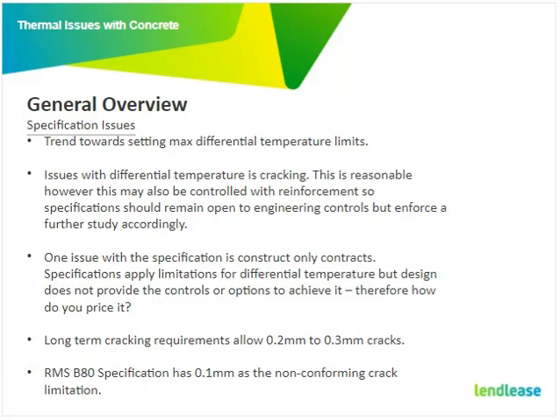Also, for differential temperature, there are long-term cracking requirements that allow up to 0.2 mm to 0.3 mm cracks, which is reasonable if you look at all the literature that's coming out at the moment. The RMS B80 specification has 0.1 millimetre as the non-conforming crack limitation. Now, the trend that we're seeing there is that the reason for that 0.1 mm crack width limit was generally to record the NCR and basically become a monitoring process. In the future, you knew where all the cracks were, and you came back and inspected them. But now we're getting forced to start repairing cracks, anything that's above 0.1 mm crack widths, which is becoming an issue.